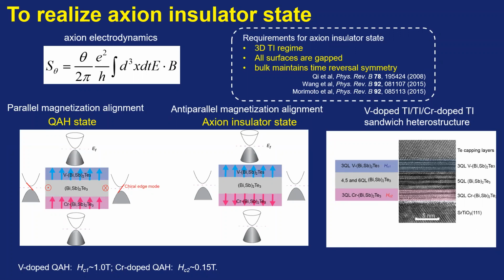So because of different HC, in some magnetic field regime, we can make the magnetization of the top layer and bottom layer anti-parallel aligned. In this kind of situation, the top surface is gapped, the bottom surface is also gapped, and there is no edge state. So this kind of state is usually called axion insulator. We find this kind of state satisfies these three conditions, so we can call it axion insulator state.